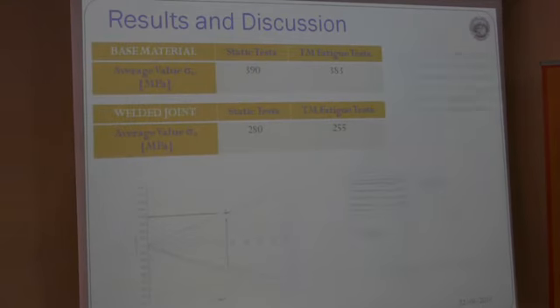A summary of the results: for the static test on base material, we see an average value for 3 specimens of 390. After, with the thermographic fatigue test, the average value for 3 specimens is 383 megapascal. After, we made a fatigue test, and at 420 megapascal we did not produce specimen failure after 2 million cycles. Now we have made the same for the welded joint, and we see the average value for the static test on 3 specimens is 250, and when we make the thermographic methodology fatigue test, we see 255 megapascal.